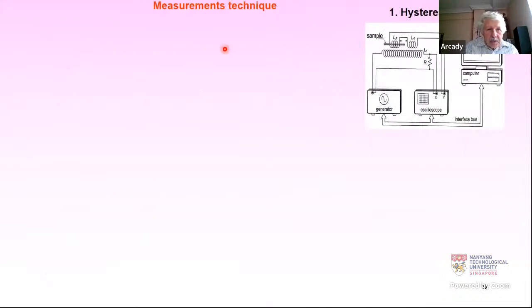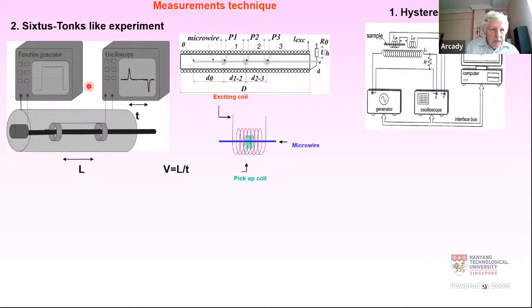In this talk, I will speak about different experimental techniques, like a method to measure the hysteresis loop. In fact, this is a conventional method, which employs just magnetizing the sample by a solenoid and picking up the signal by pickup coils. And we also measure the domain wall dynamics by Sixtus-Tonks-like experiments. So in this case, there are 2 pickup coils, but usually we use several. Once we measure the domain wall travel time along the sample and the distance, we can calculate the domain wall velocity.